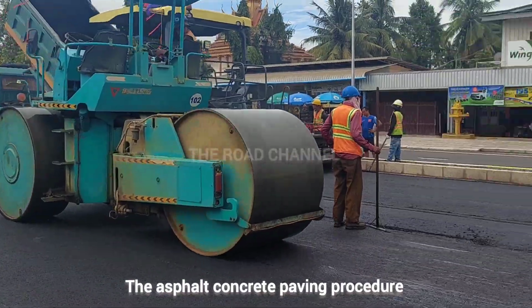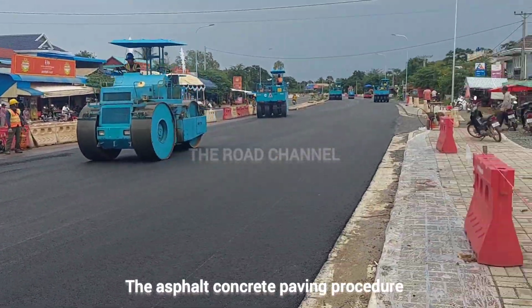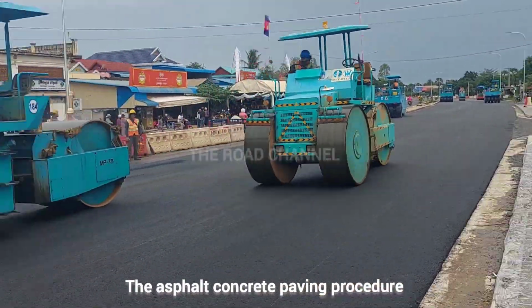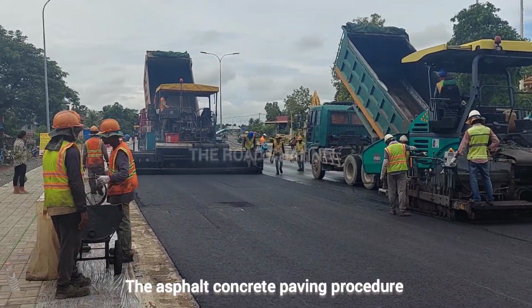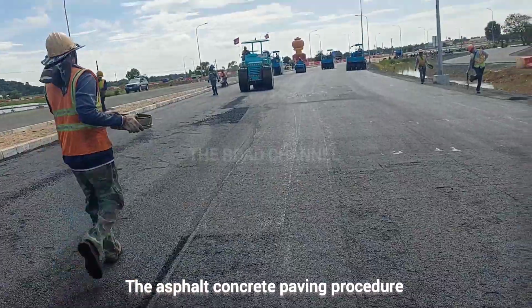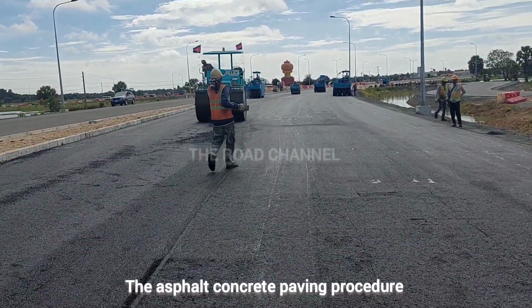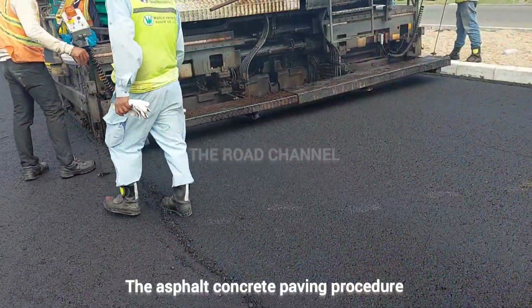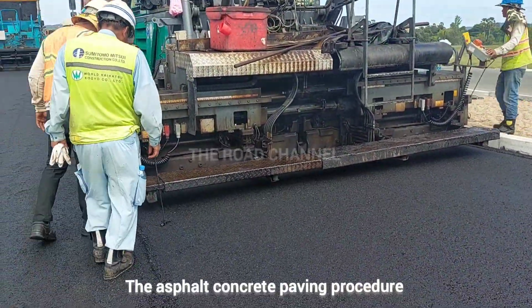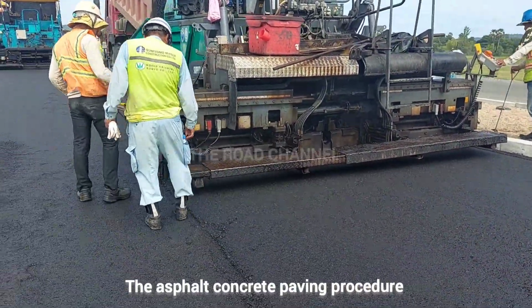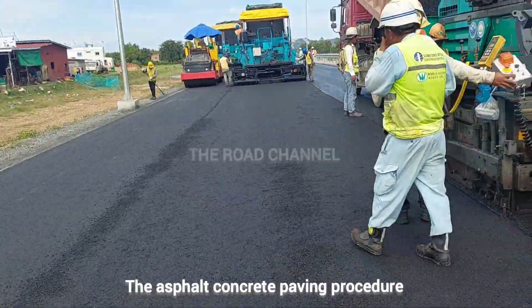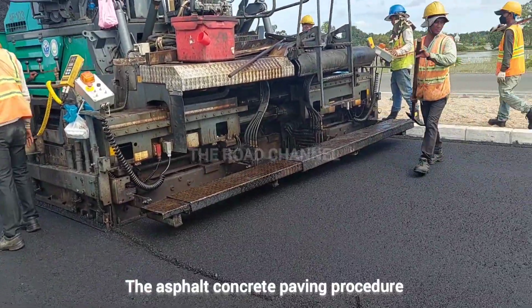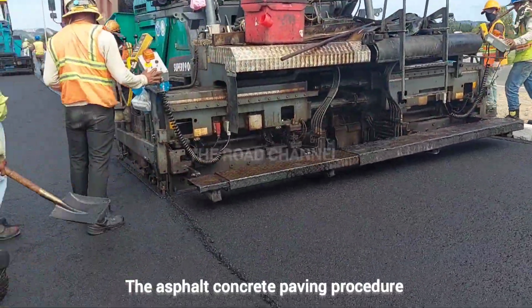5. Quality control and finishing. Density and thickness check. Conduct field tests, such as nuclear density gauge or core sample testing, to ensure compliance. Surface evenness. Check for uniformity, avoiding segregation, rutting, or cracking. Cooling and opening to traffic. Allow the binder course to cool and cure before proceeding with the surface course.